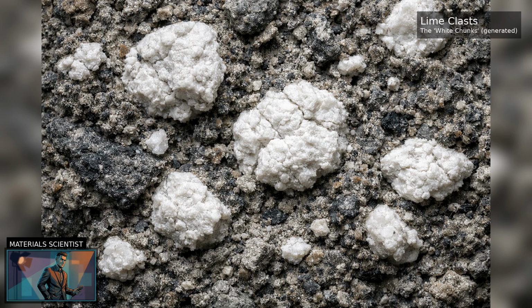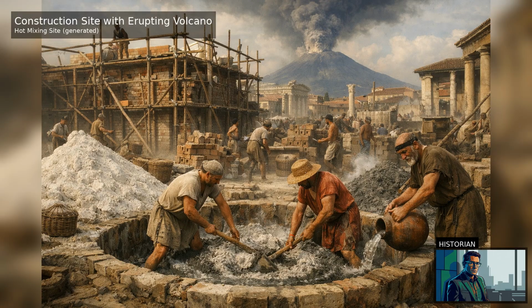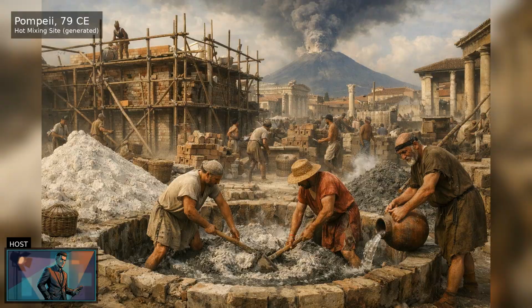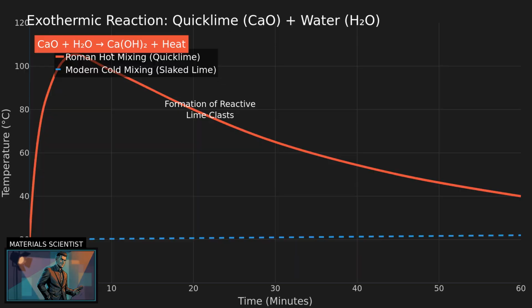But if the same mistake shows up again and again in long-lasting Roman mortar, you start asking whether it was intentional. The big clue came from Pompeii, a house mid-renovation when Vesuvius erupted in 79 CE. Basically, a work site paused on the clock. A study published on December 9, 2025, analyzed the raw materials left there and found strong evidence the workers were using a technique researchers call hot mixing. Hot mixing, like they heated the water? No, the chemistry makes the heat.